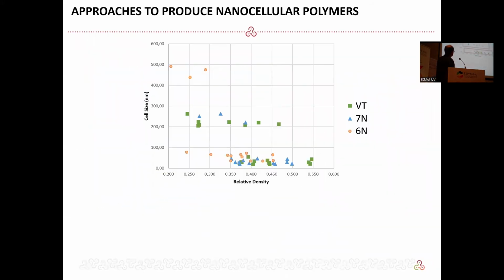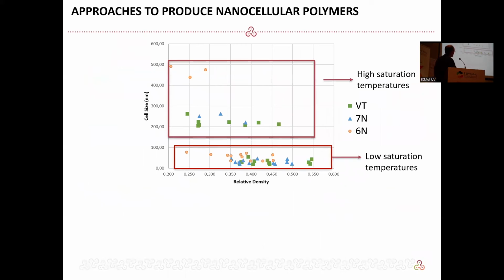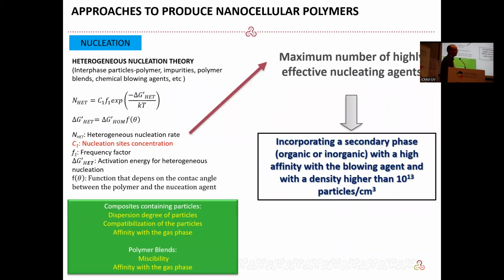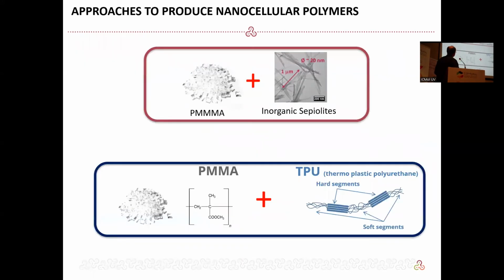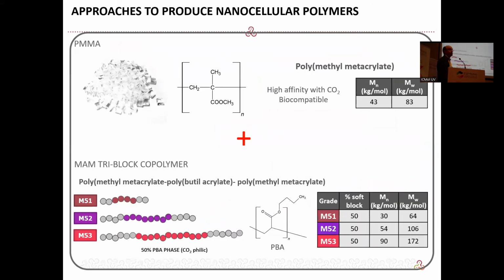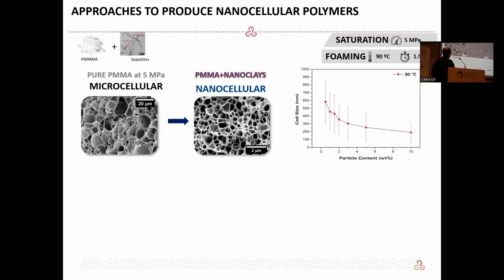Okay, so this is one example of what we can produce. Also, we can play with the polymer. Different polymers with different molecular weights give you different nanocellular polymers. And second, I will show you the heterogeneous, just two examples. In the heterogeneous nucleation, we introduce nucleating agents into the polymer. Nucleating agents could be particles, for instance, nanometric sepiolites. It could be the mixing of two immiscible polymers, PMMA plus TPU, polymethyl methacrylate plus thermoplastic polyurethane, or it could be the combination of polymers that are miscible.